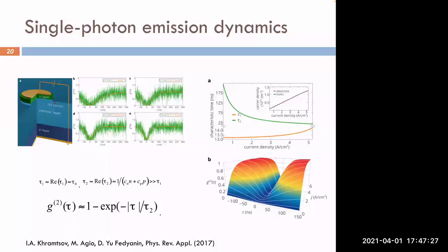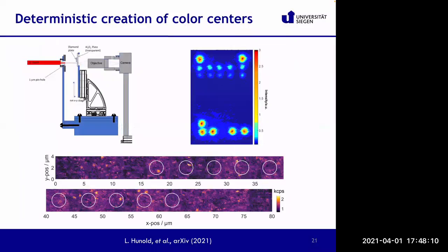And this can be clearly seen also in the experiments that have been done in Stuttgart on the nitrogen vacancy center, and that we interpreted correctly with this theory. So, without going into the details, you can see that by changing the current density, you can really change not the nature of the single photon emission, but the G2 function, from something that has a time constant of several nanoseconds to the typical time constant of optical excitation, which is of the order of 10 nanoseconds for the nitrogen vacancy. Okay, so this is about